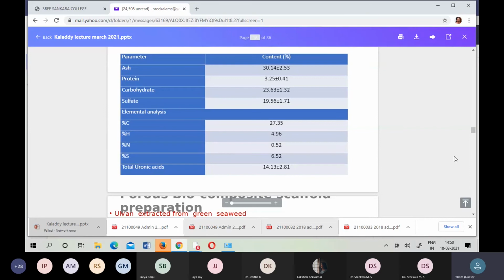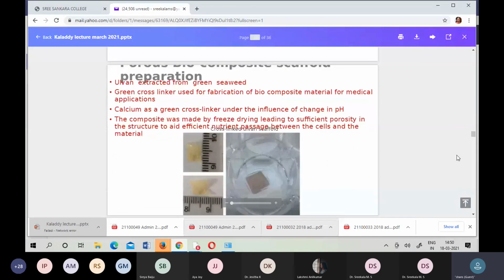So we made scaffold, like 3-dimensional, 2-dimensional. First, we made the film, and we were very sure we were able to make the films, but we wanted to go for the bio scaffolds, 3-dimensional. We made a small scaffold structure, like the cubical structure at our lab. The Ulvan solution is water soluble, so we dissolve it in water, and instead of commercial cross linkers like glutaraldehyde or dicarboxylic acid, we use calcium chloride. Calcium is a green cross linker, and this is ionic cross linking, not covalent.